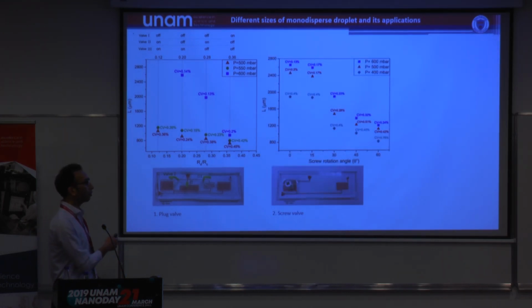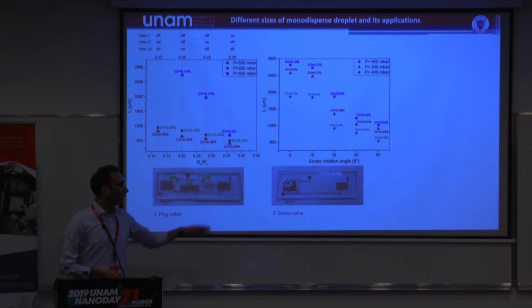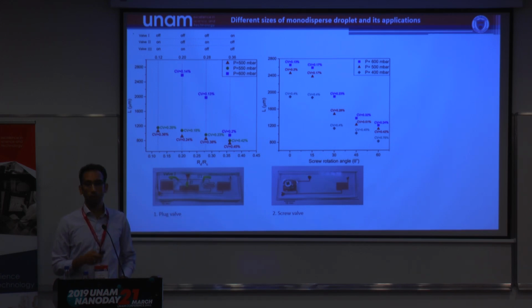We used a microplug valve. We had a different configuration for on and off those valves. And we used a screw valve in order to change the thickness of the channel. And by changing the thickness of the channel, we can change the hydrodynamic resistance of the channel. So we will have different sizes of the droplets.